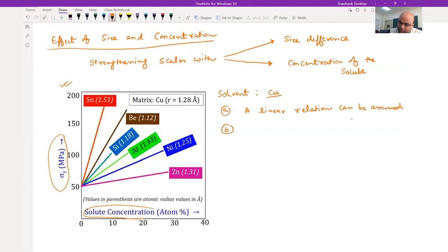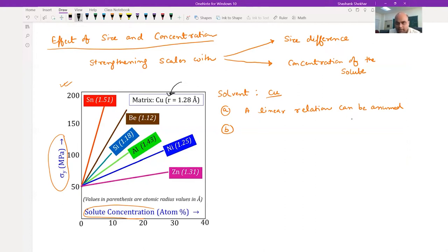The second difference you see is: copper has a radius of 1.28, and I have listed the radius of other solute atoms in brackets. You can see that larger the difference between the radius of copper and the solute atom, the higher the magnitude of yield stress. Tin, which is 1.51 while copper is 1.28, has the largest difference - so at each solute concentration, when you add tin in the copper matrix, you have the highest yield strength.